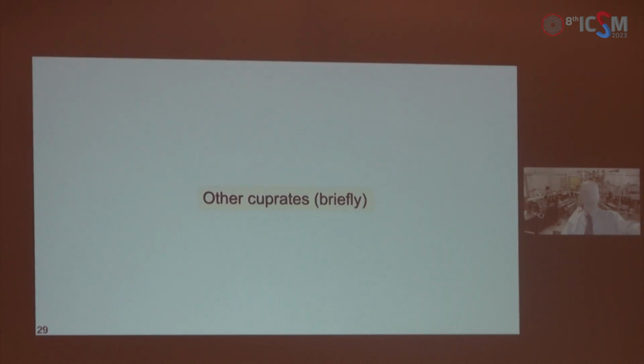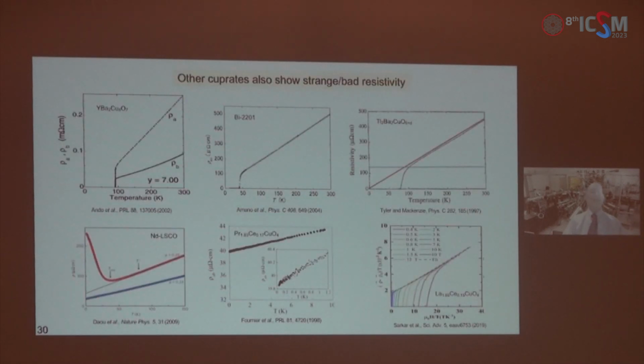I won't have much time to talk about other cuprates, but let me just make a general remark that most of what I said applies to all of them and is actually universal. They are all strange metals, meaning that the resistivity can be linear in temperature at some doping levels, and in several cases this linearity persists down to dilution fridge temperatures, a few tens of millikelvins. And the fields that are tested are also what I have called doubly strange, meaning that the resistance is also linear in the magnetic field.